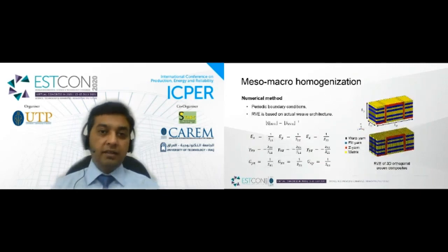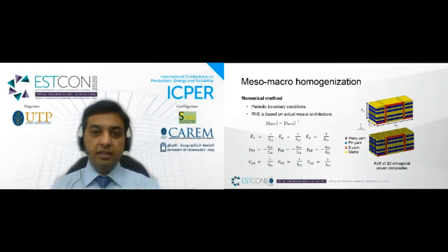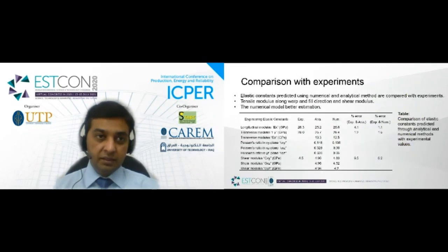Now, in the case of the numerical method, similar to the micro to meso homogenization, periodic boundary conditions were applied on the representative volume element discussed earlier. Once we know the compliance matrix, the stiffness matrix is determined by taking its inverse. Here the elastic constants are determined in the global coordinate system, which is XYZ. Now, the comparison of predicted elastic constants with experiments.